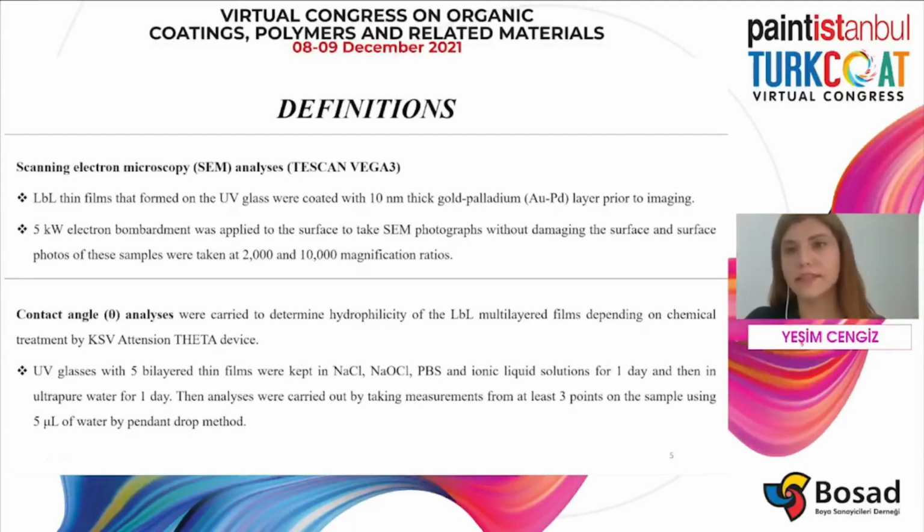About contact angle analysis, we used the KSV Attension Theta device, and UV glasses with 5-layer thin films were kept in some ionic solutions: sodium chloride, sodium hypochlorite, PBS, and IL for 1 day, and then in ultra pure water for 1 day. After that, measurements were taken from at least 3 points on the sample, using 5 microliters of water by the pendant drop method.